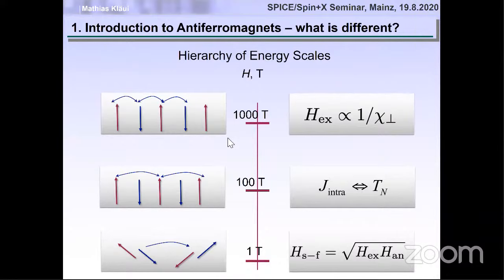Hi. Good. Just a comment or maybe a question about what the energy scales are here. At least from molecular field theory, I know that the Néel temperature depends on nearest neighbors as well. Then I'm a little bit surprised that you could distinguish between nearest neighbor and next nearest neighbor, because from microscopic calculation, we can show that the Néel temperature depends on the nearest neighbor coupling, which is antiferromagnetic.